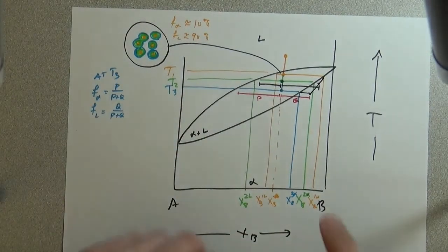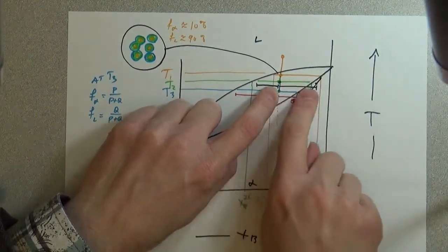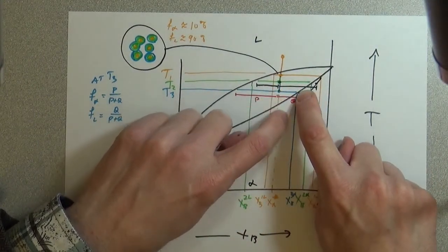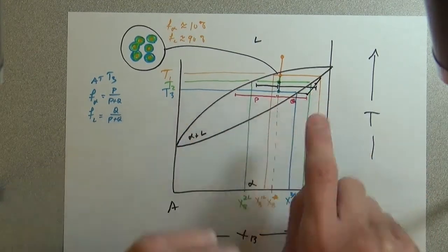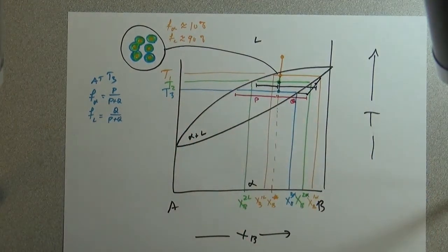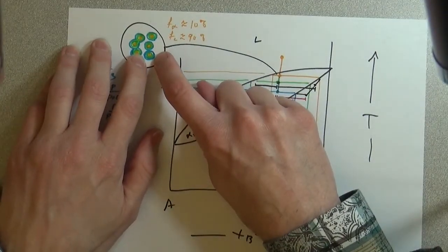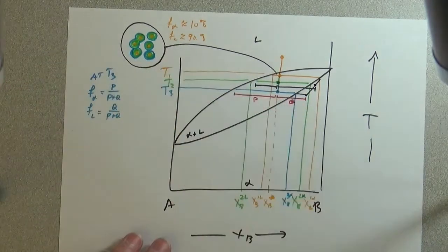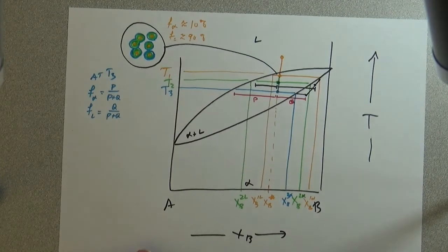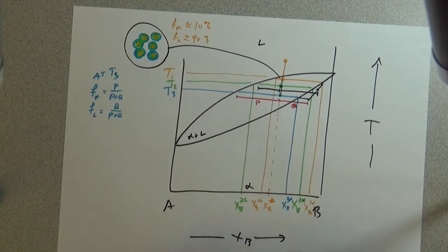Now the thing is, because we're pushing this phase boundary further to the right, what we're essentially doing is saying that there's less total volume fraction of phase that forms relative to the liquid, but it's richer in B because the interior has excess of B atoms.